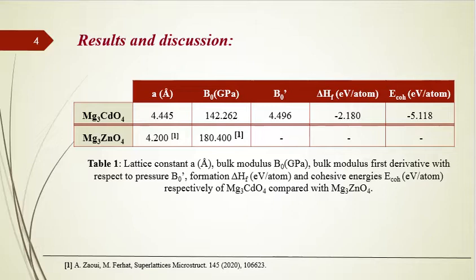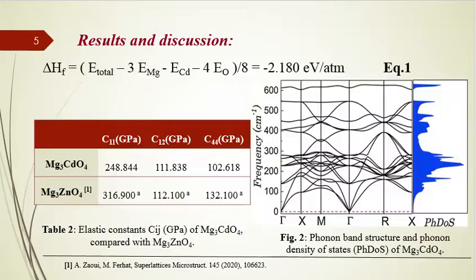Second, and according to the elastic constants given in Table 2, it is also locally stable. Moreover, the phonon spectrum of Figure 2 shows no negative frequencies. Consequently, the material is stable.